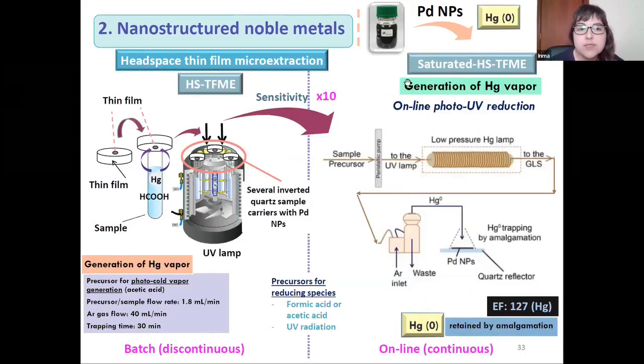Then, using the same palladium nanoparticles, we have another application. Instead of using sodium borohydride as the reducing agent, here we use photochemically generated mercury. For this reaction, we need formic acid or acetic acid as the precursor for the reducing species, and also ultraviolet radiation. And then we perform two tests.